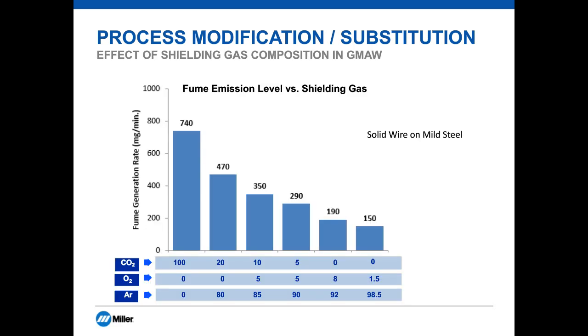This slide shows the effect of shielding gas on fume generation rate for gas metal arc welding. The results are similar for flux cored arc welding. The bottom line is that the less active the shielding gas is, that is, the higher the argon content, the lower the fume will be.